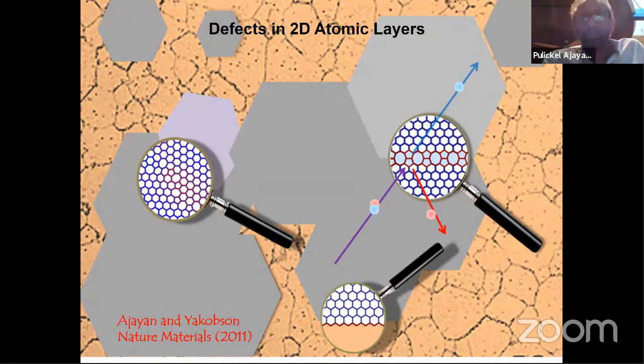And people have again looked at these in more detail and found these topological defects at grain boundaries. There's also suggestions that depending on how these grain boundary structures are created, you could in fact have significant scattering of electrons or even tunneling of electrons. Some of these things have not been experimentally verified, but certainly it looks fascinating that such grain boundaries would exist, with the properties that they have.